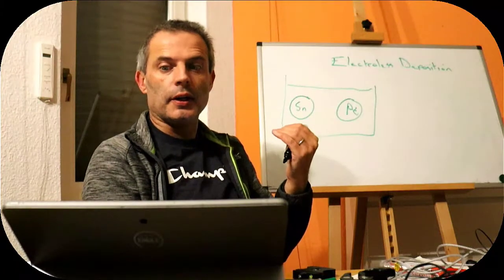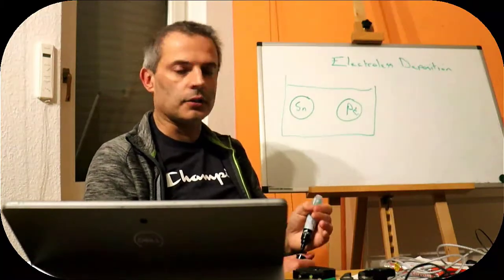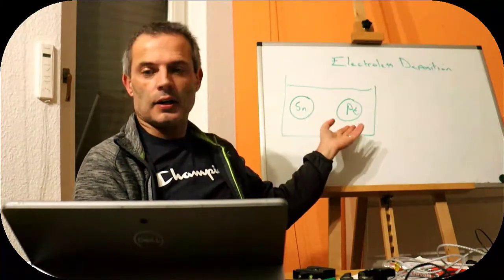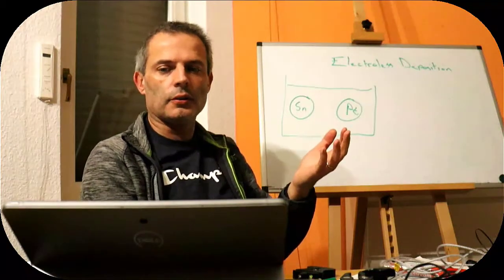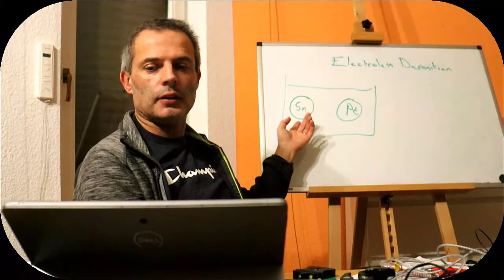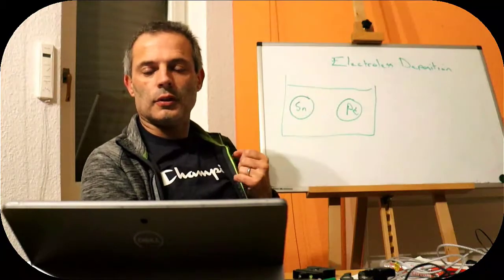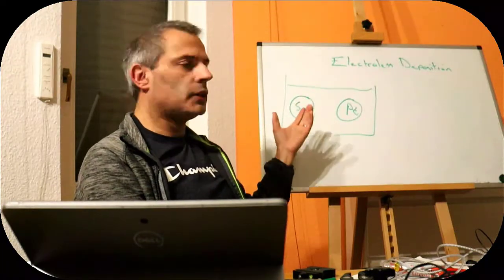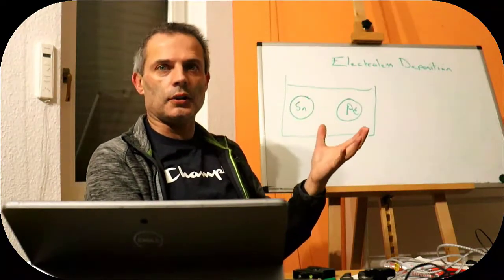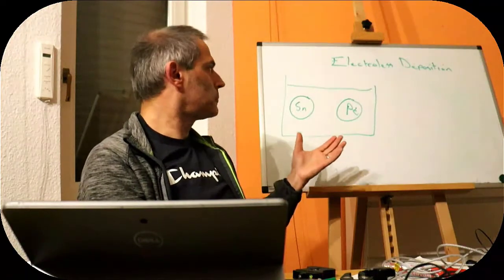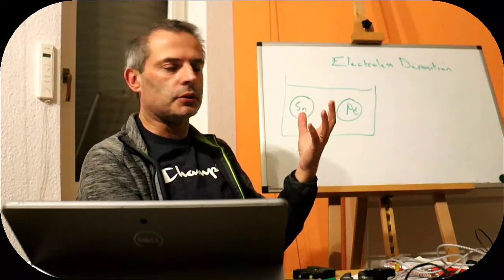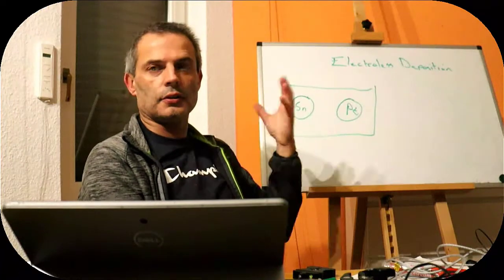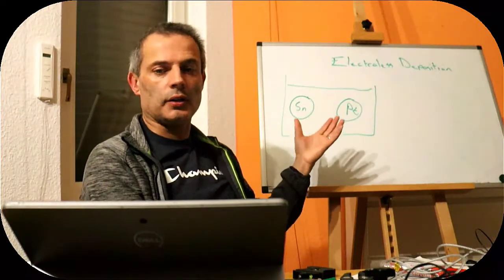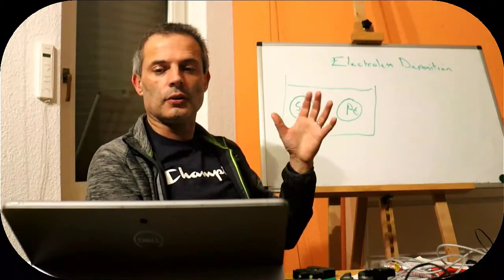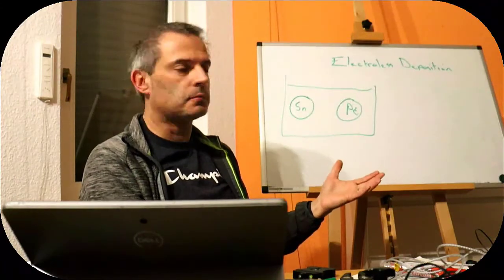We can get a little bit there by looking at the demonstration that I did with tin and platinum. You can look that up. If we take a piece of tin, it is reducing enough to generate hydrogen in a slightly acidic solution. But the overpotential for making hydrogen at the surface of tin is quite high. It's difficult to make hydrogen on tin, and so nothing happens.